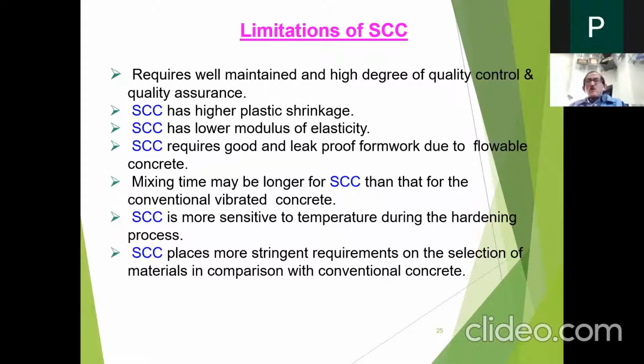So mixing time may be longer than that for conventional vibrated concrete, because there is more paste, and because the particle to particle interaction and dispersion should be proper, and because of the use of VMA, viscosity modifying agent, you require a little more mixing time. Then SCC is more sensitive to temperature during the hardening process, and SCC places more stringent requirements on the selection of material. So the requirements are stringent, the quality control required is more, the plastic shrinkage is higher, the modulus of elasticity is lower. But these are very marginal compared to the advantages, and the advantages far outweigh the limitations of self-compacting concrete.